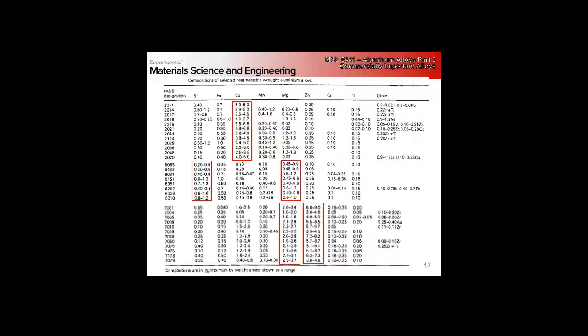We've got the ranges here where we're higher in zinc than we are in magnesium. Just an observation here that I don't remember if I made during the age hardening discussion: what's the crystal structure of magnesium and zinc? HCP. And we'll also see that in some alloys we add zirconium, which is also HCP. So with a different crystal structure we tend not to have the larger degree of solubility. That helps us with our high curvature of the solvus, and we will precipitate these out more.